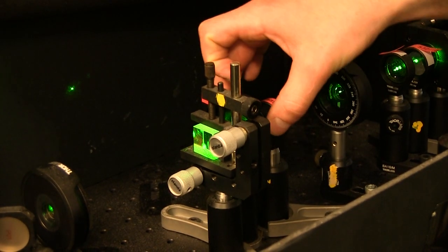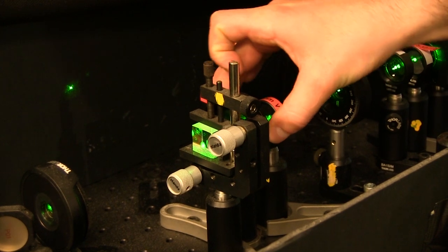We repeated this over and over and we understood by carefully analyzing the influence of the laser intensity that in fact at low power the domain wall was staying at the same position, but at high power it was moving with the position of the tip. So it was not expected, we found out this way just by playing with the power.